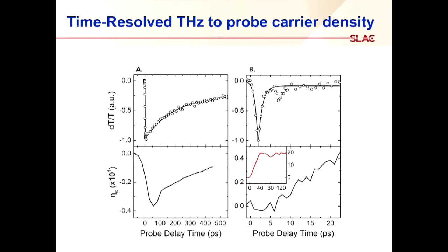let me give you an extra part of an experimental clue. What we wanted to understand was a little more about what was happening in the material during that time period, and also to explain the fact that this compressive phase was observed in some of the materials in the family and not in others. So we were able to make a very nice correlation by doing a low-frequency optical measurement on the same samples under the same conditions. We looked at the carrier density that we produced. We did that by looking at the induced conductivity measured with low frequency radiation, with terahertz radiation.